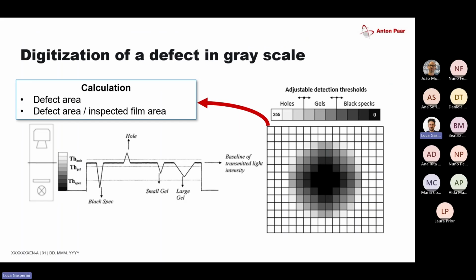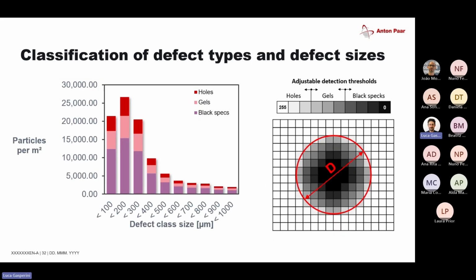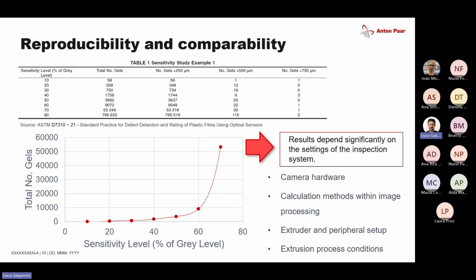And the software essentially calculates the defect area, any deviations from the baseline, counts the pixels and applies a sphere within the area to give the defect a diameter. And if you do this in a continuous process, you get a distribution of different types of defects of different sizes, which gives you an indication about your film quality. Naturally, this whole process depends on the settings you use, what kind of defects you want to detect, and the focus of the camera.